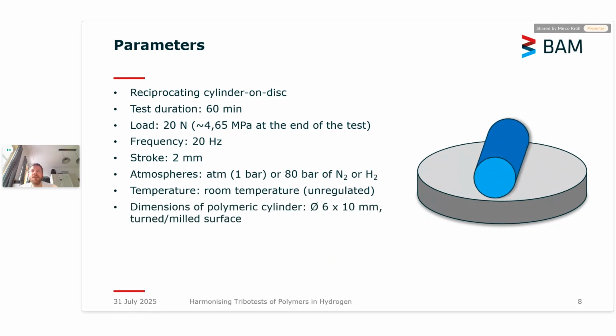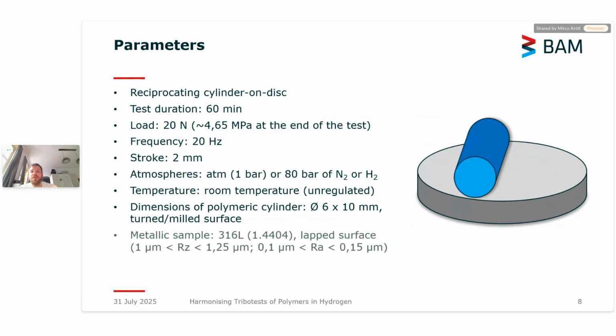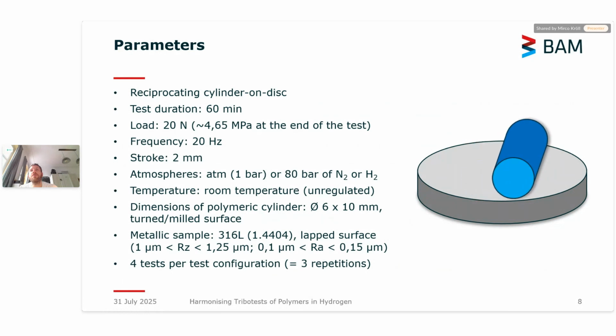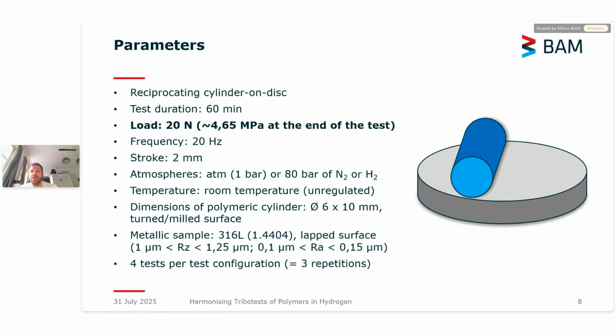The polymeric sample was a pin or cylinder with a diameter of 6 millimeters and a length of 10 millimeters with a milled surface. And the metallic disc was made of 316L with a lapped surface. We did 4 tests per configuration per parameter set, which means 1 test and 3 repetitions.